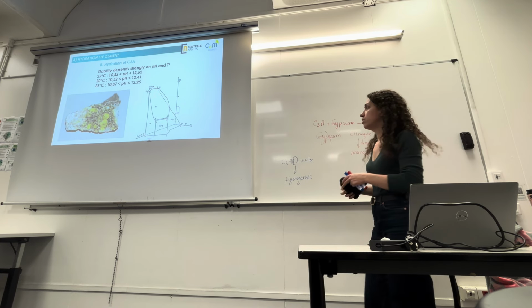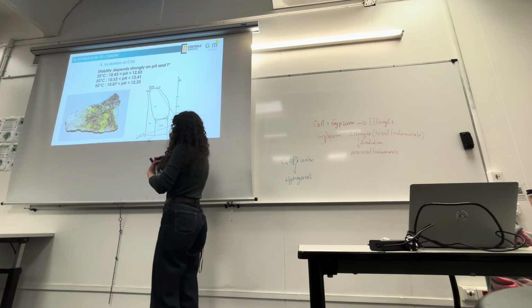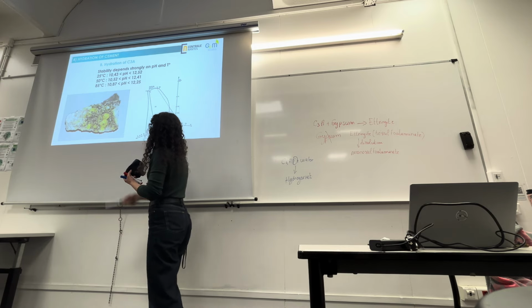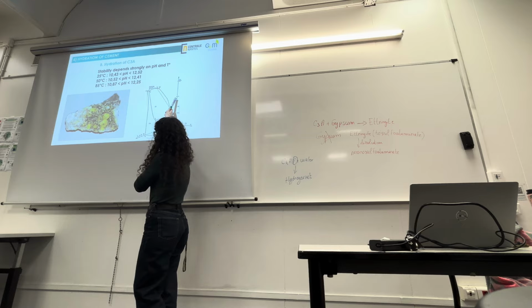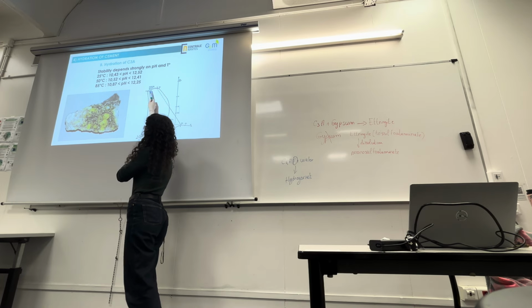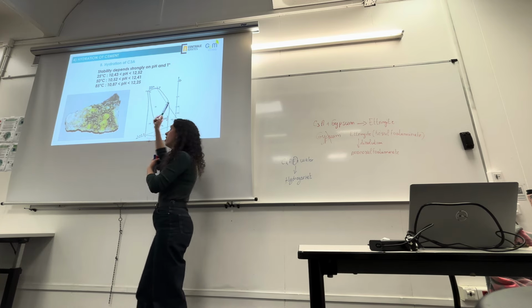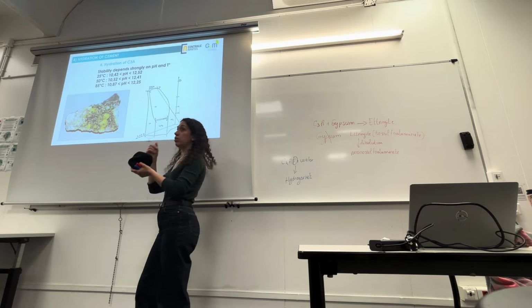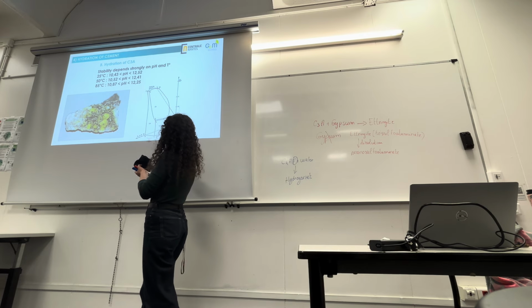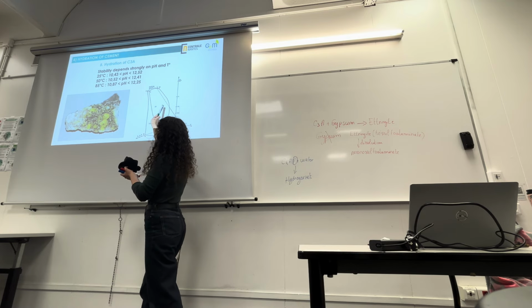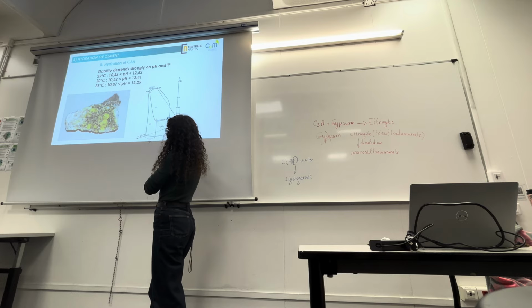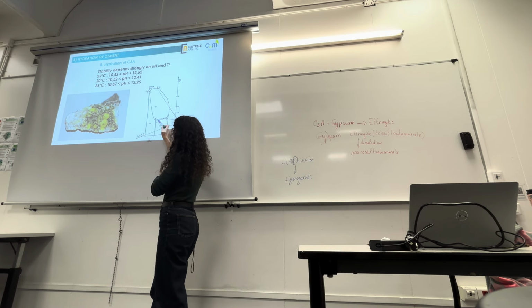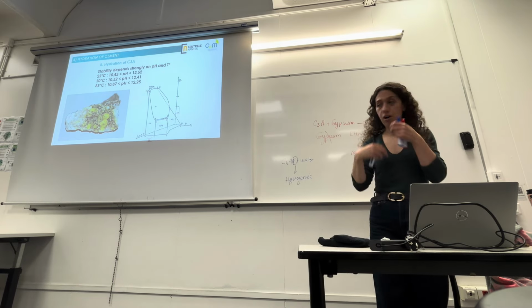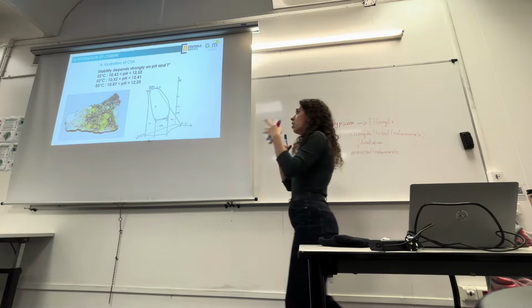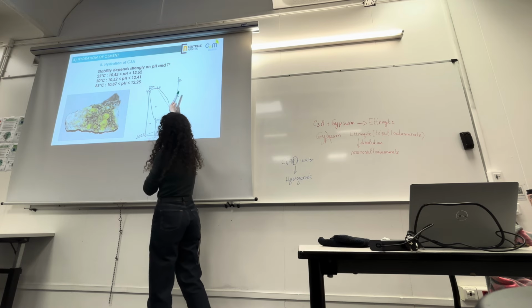So I have a diagram of stability of the calcium aluminum sulfate phase. You can see when the sulfate concentration is very high, you are in the territory of gypsum. So if you have a very high sulfate concentration, you would precipitate gypsum. But it's not the case in the cement. In cement, you will have mostly aluminate and calcium. And then here you have ettringite territory. And once you reach a lower sulfate concentration, you get into monosulfoaluminate territory. So the stability of the hydrates, especially ettringite, depends on the temperature, on the pH, and also on the concentration of sulfates.